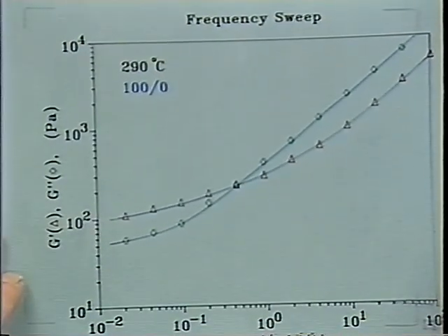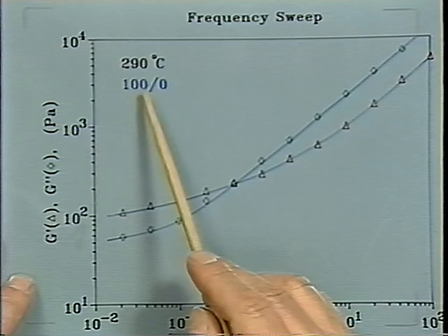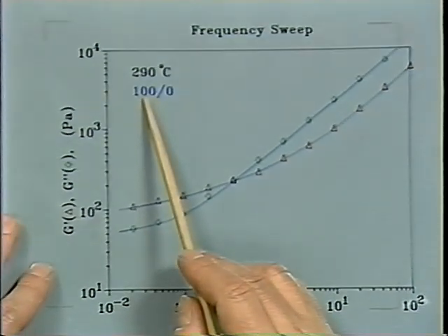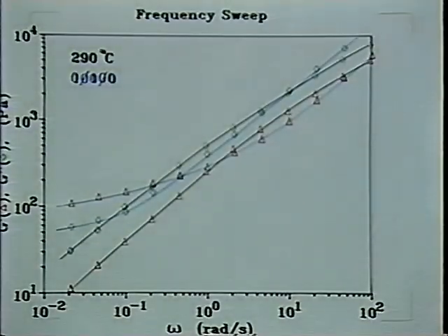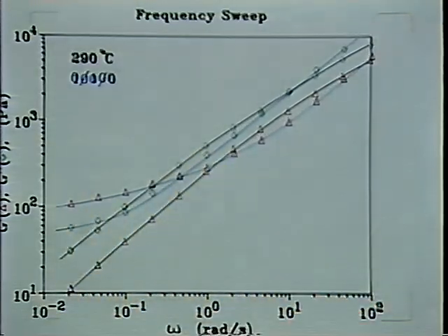This is linear viscoelasticity, which is possible at low rates. This is 100% of the Vectra material. So again, the first number indicates the Vectra here. And you saw that also already from Sugaski's data. Now, the spectrum of the Tennessee Eastman material is much lower. Maybe I should superimpose that. It's more liquid-like. Actually, the liquid range is accessible in the system. They are drawn on the same scale. You can see that at low frequencies, somehow the Vectra material levels off and the Tennessee Eastman goes down.